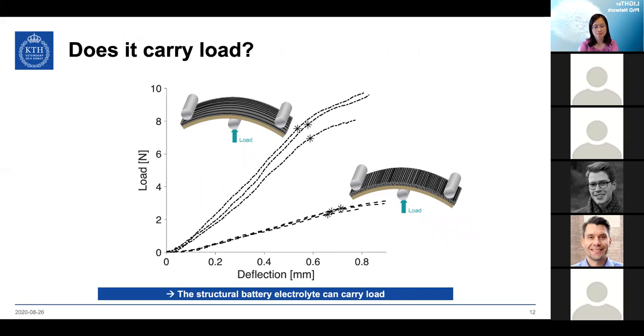For this, we investigate the stiffness and strength of the structural battery electrolyte combined with carbon fibers. This is done by testing samples in 3-point bending and measuring the stiffness and load at failure. The data shows examples of results in the longitudinal and transverse direction in relation to the carbon fibers. The values are between 90% and 50% as good as samples with pure vinyl ester. This shows that the structural battery electrolyte can sufficiently distribute loads to the carbon fibers to carry load.